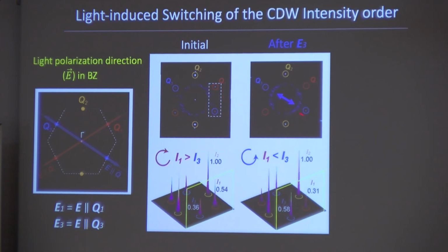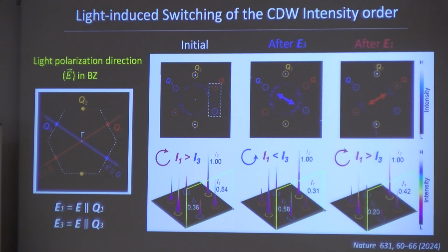And now shine light in this direction. This is brighter than this. And now shine light in this direction again, and it reverses. This is brighter than this. Can you see that? Can everybody see that? So by shining light along a certain direction of the charge density wave order, we can make the intensity of the CDW peak higher in that direction.